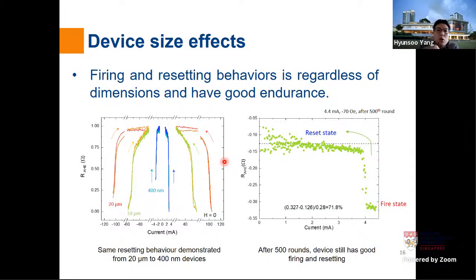We can also show at zero field. In this case, there is no deterministic switching, so we can fire in any direction. We can apply negative current and positive current, and we can fire and then go back to zero current, and that will also bring us to the initial magnetization direction. So basically, we already demonstrated this device doesn't require any reset pulse. And then we also scale the device size and see what happened. This red one is 20 micrometer width of the channel.